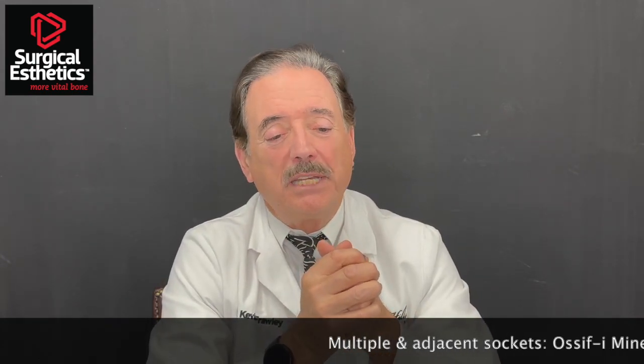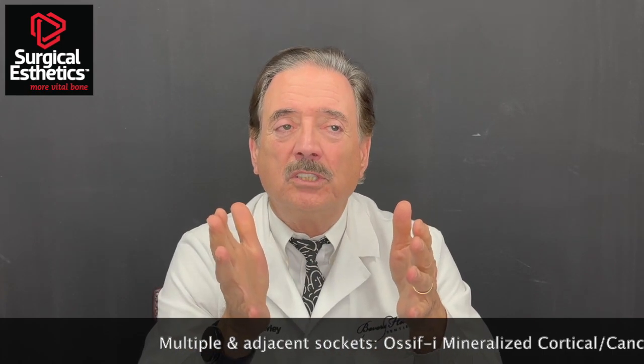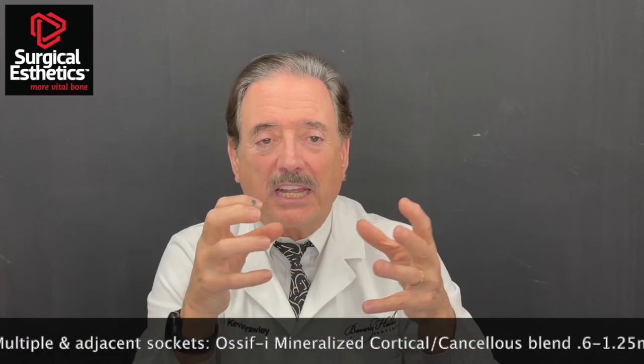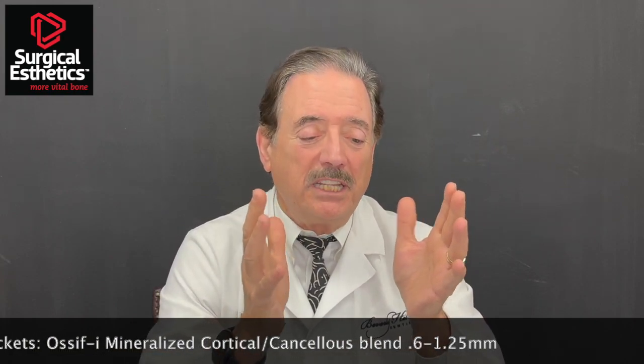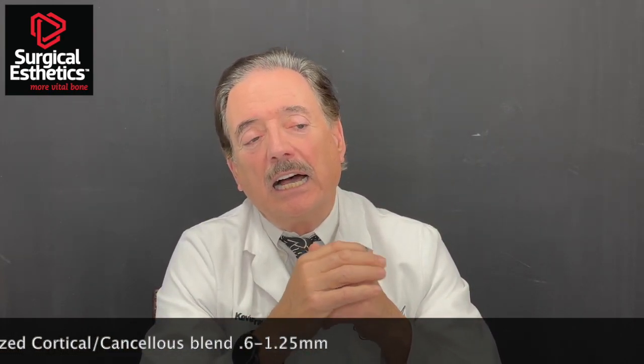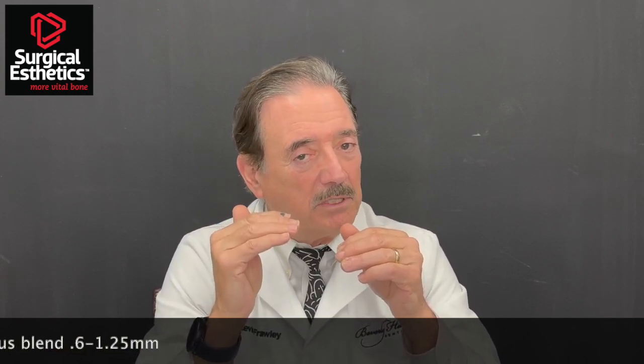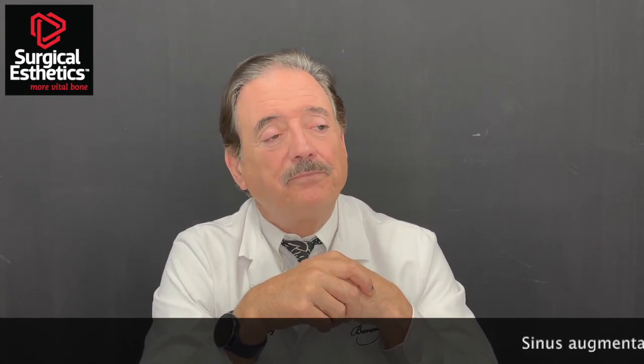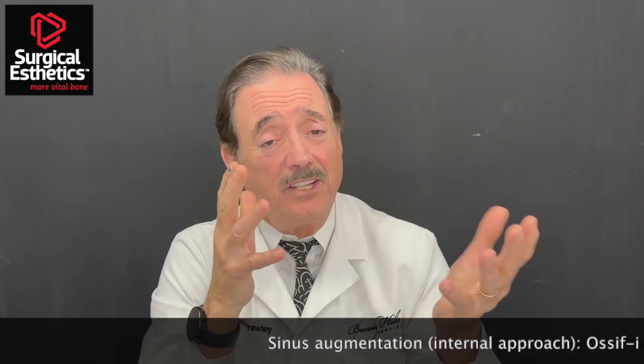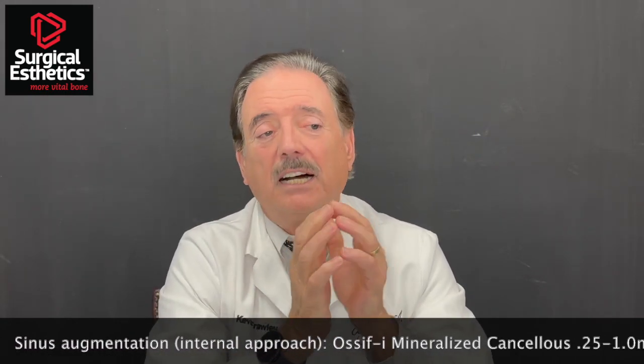If you have multiple sockets against each other, the potential for the interproximal bone to resorb is greater than if you're grafting against a tooth. If a tooth is there in the adjacent space, the height of the interproximal bone will generally be very stable. So if you're doing 2 extractions next to each other, the interproximal bone height is not as stable. And so that's a place where I would use the cortico-cancellous as well to help maintain that bone height as much as possible. In a sinus, you can pretty much use either mineralized cancellous or cortico-cancellous.